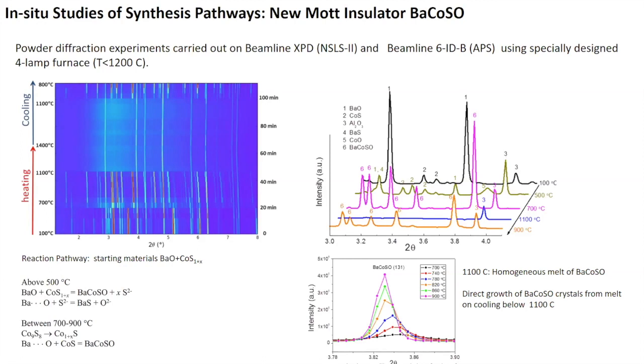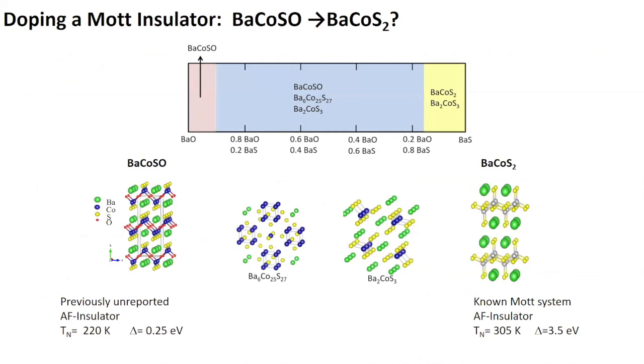I can't go into the details because of the time issues, but in this particular case, we were able to use our in situ experiments basically to explore the entire phase diagram from this side, where you have just barium, sulfur, and cobalt. This is BaCoS2, which is a known Mott antiferromagnetic insulator with a large gap and Néel temperature slightly above room temperature. And you can see that as you start to mix barium oxide in for the barium sulfide for a large range of compositions, instead, our experiments show that you get this barium cobalt sulfur oxygen phase, as well as 2 other ternary phases.